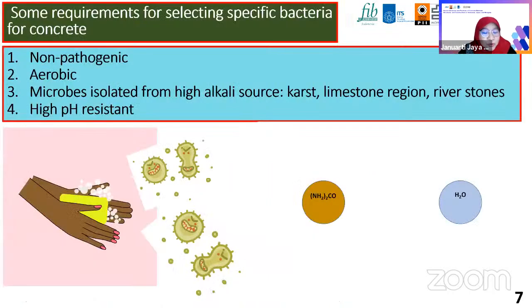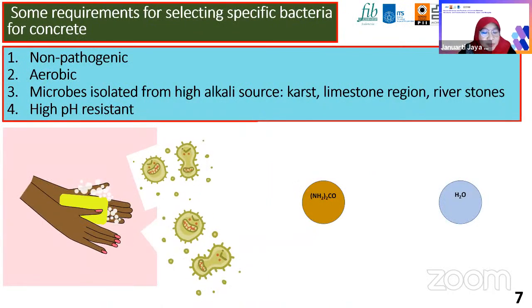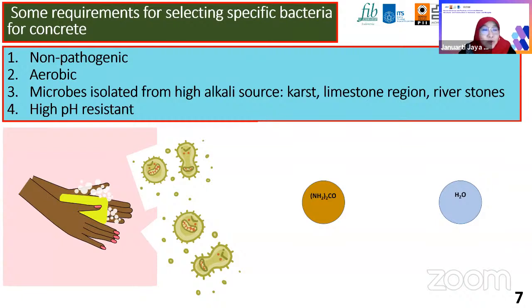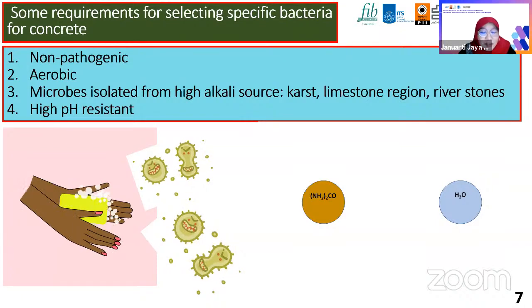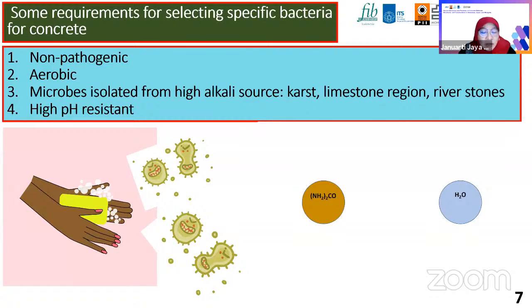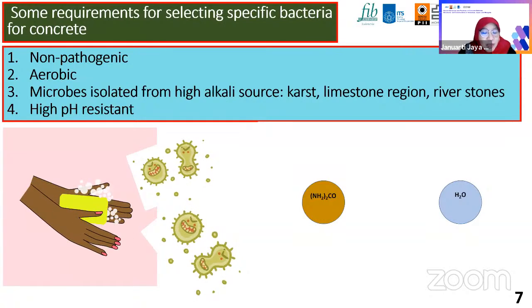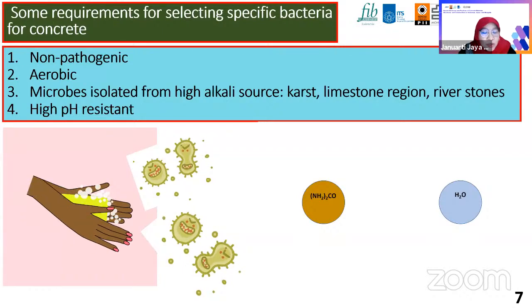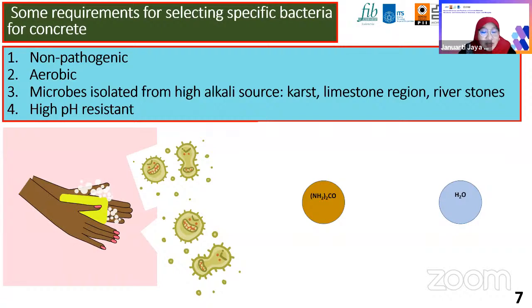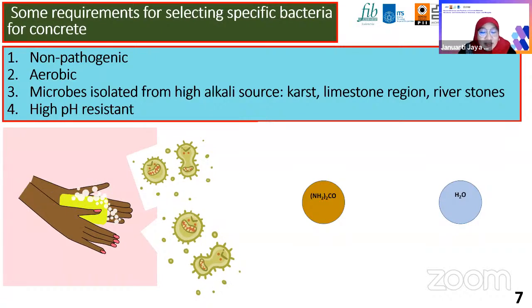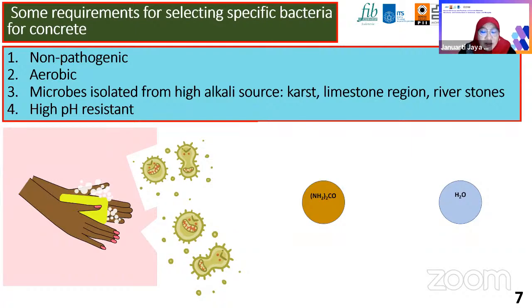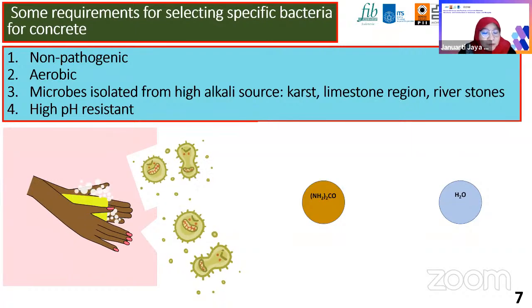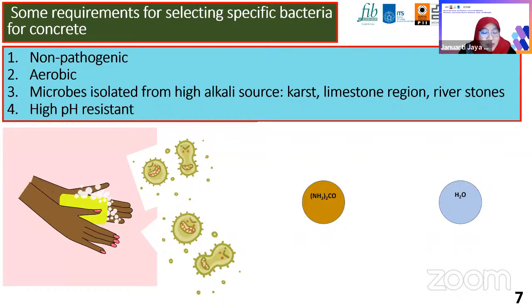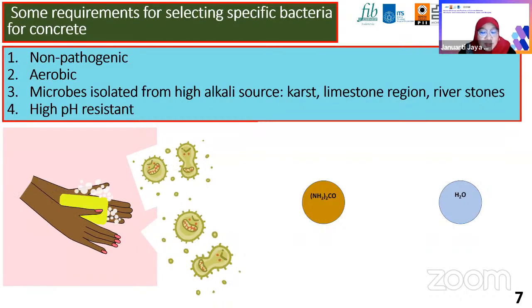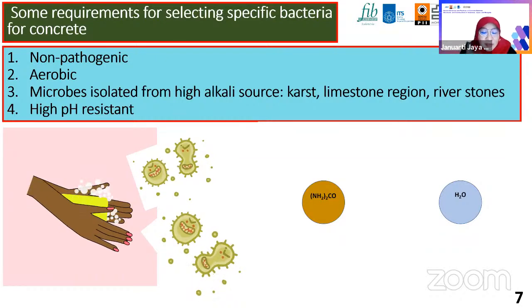So this is, I have to emphasize here, the microbe selections. Obviously, we have to use non-pathogenic aerobic bacteria. We don't want to get sick because of this kind of bacteria. So it should be non-pathogenic bacteria. And it has to work to fill the pores if the oxygen exists. As concrete containing lime, the pH may be a bit higher, and the microbes have to stand high alkalinity. So we isolated the bacteria from lime source, a very local place in East Java.